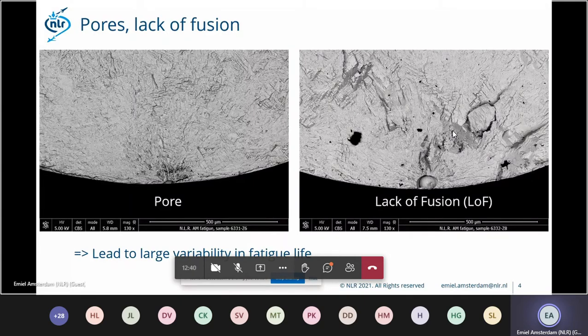So here you can see a pore in a fracture surface. This is a scanning electron microscope image. And here you can see a pore from which a fatigue crack started to grow.